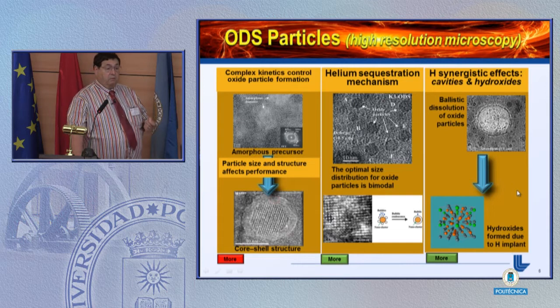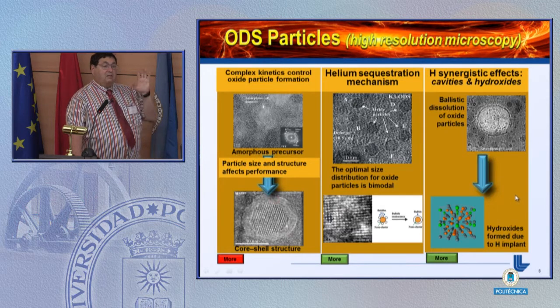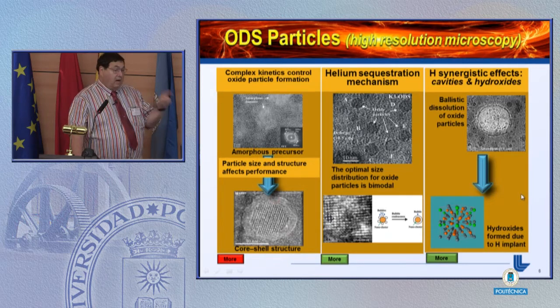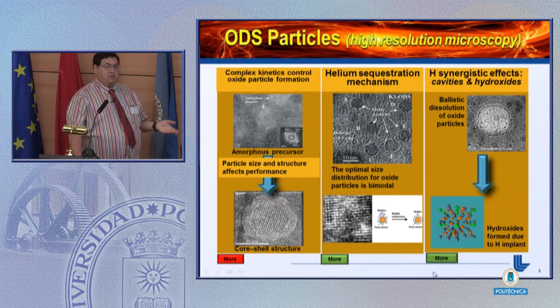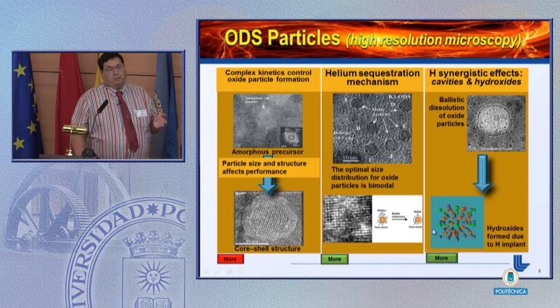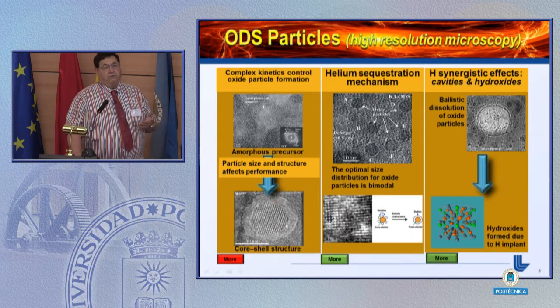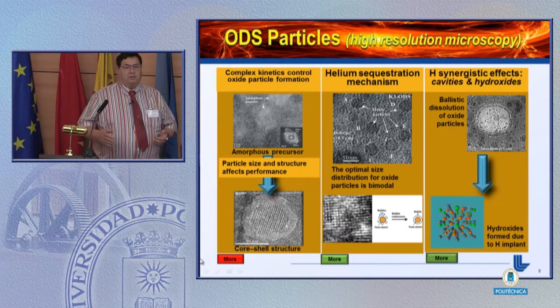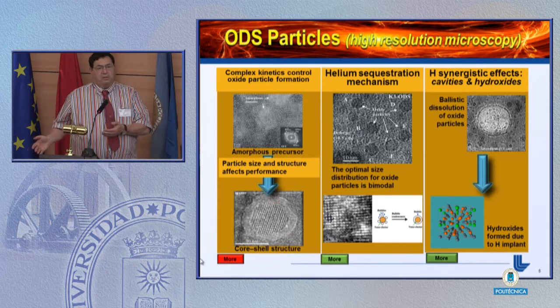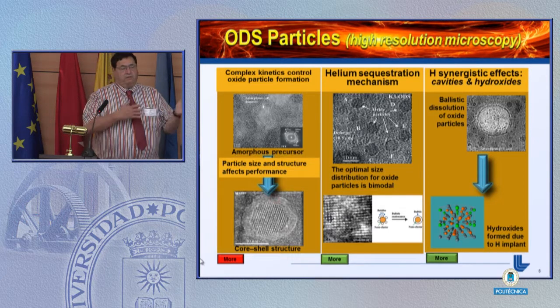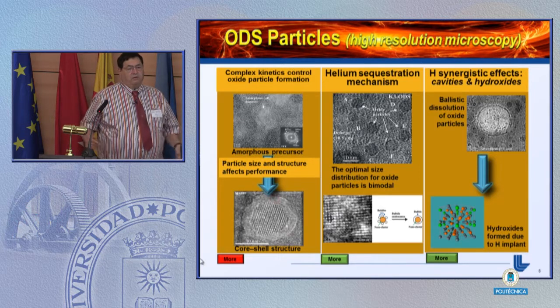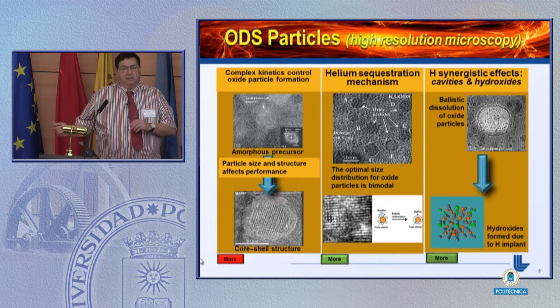And they saw that when they irradiated with hydrogen, helium, and heavy ions, they got 10 times the swelling that they got when they irradiated helium and heavy ions or hydrogen and heavy ions. So there was something synergistic going on. And these effects were taking place at temperatures where normally hydrogen would diffuse out of the material. And so suddenly the community divided itself into two parts. There were people saying, there's something wrong with these experiments. We know that hydrogen is a fast diffuser, and at temperatures of 500 degrees, which is where these experiments were done, there's no hydrogen in the system.